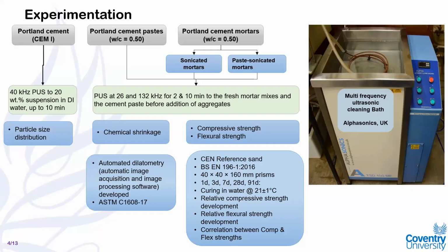In this experiment, the results I'm presenting are related to part of the results we obtained from particle size distribution of Portland cement. Then we focus on cement paste and mortar, both with a water to cement ratio of 0.5, both treated by a bespoke multi-frequency ultrasonic bath designed by Alphasonics UK, operating at 26 and 132 kilohertz for 2 and 10 minutes.